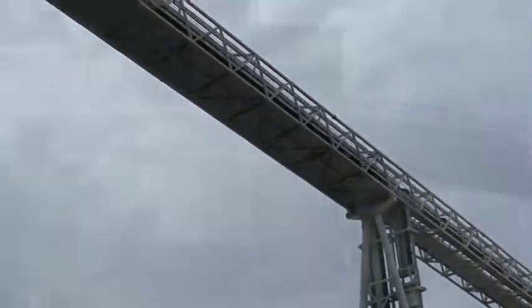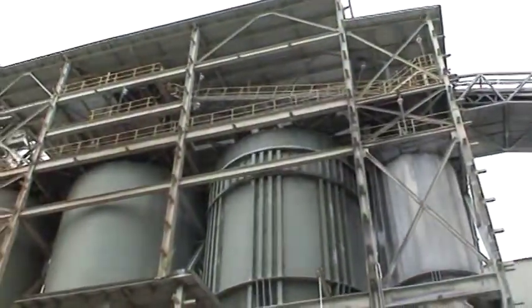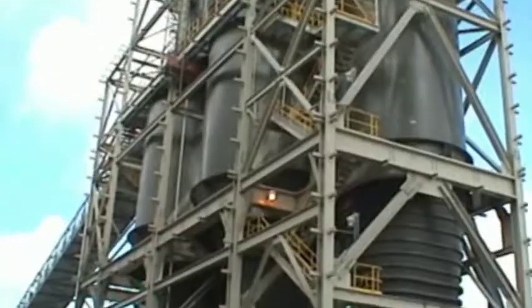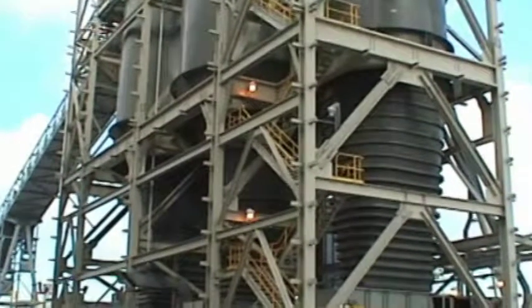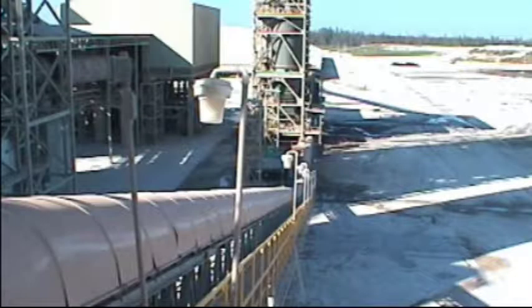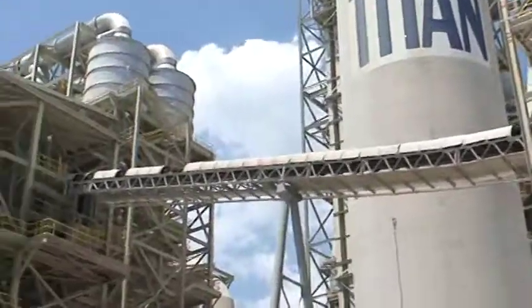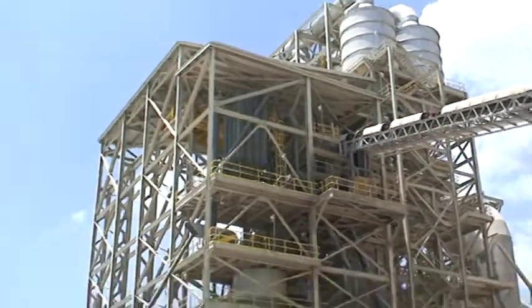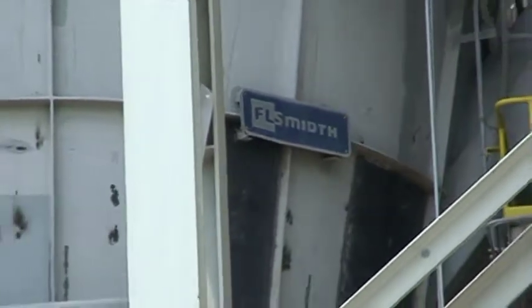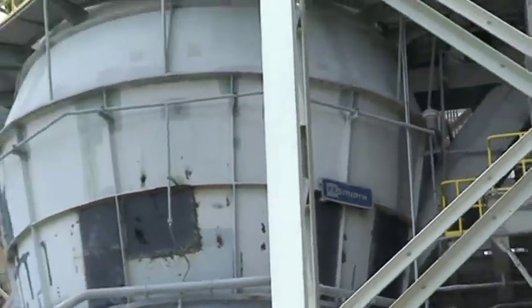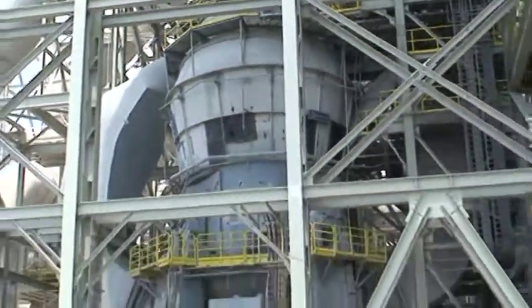All are reclaimed and end up here in the raw mill bins, where feeders underneath each bin feed material onto a conveyor passing under another ACES, which adjusts each feeder automatically, keeping a uniform chemical composition all the way to the raw mill. Once entering the raw mill, the combined materials are ground by 4 76-ton rollers to achieve a fineness average of 12% on a 170 mesh.